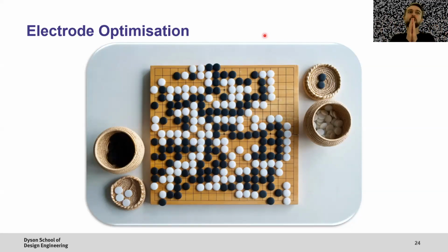One of the things that you find when you're trying to do in silico optimization is that your optimizer will very likely just find your assumptions. So your model will always contain assumptions and simplifications necessarily. One of the things you should be very cautious of can be clarified by this example. If you say, well, I'm making a fuel cell and gas transport doesn't matter, because the solid state diffusion is so much harder, but in your model you turn gas transport off, then don't be surprised when the pores close.